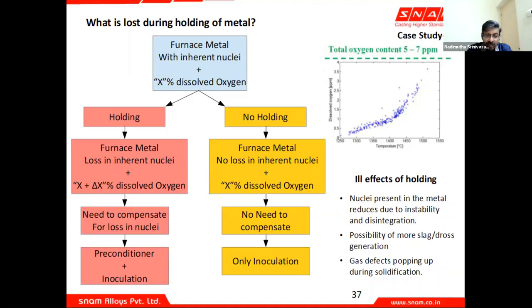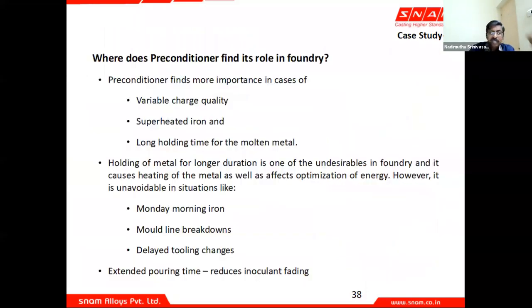So how do you compensate for this? By adding preconditioner. What exactly happens is, when you have an excess of dissolved oxygen, the minute you take it for magnesium treatment, the oxygen and magnesium react, and along with this violent reaction, there is an exothermic reaction when the magnesium burns, and all the other nucleating elements, their oxides also get destroyed, and you have slag formation, and the nucleation sites are lost. So when we add a preconditioner, it adds an excess of the nucleating elements like barium or calcium, and they are retained. So that provides the nucleation sites.